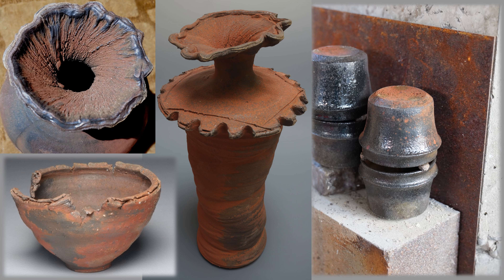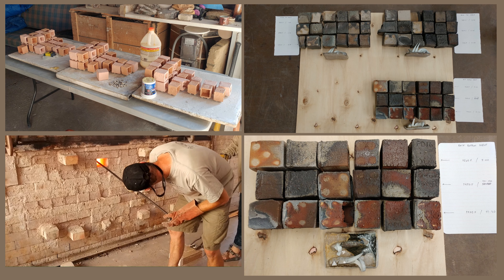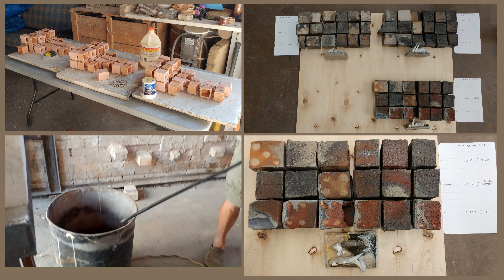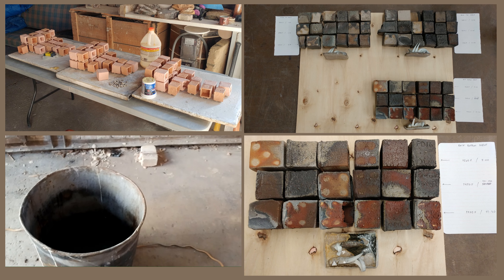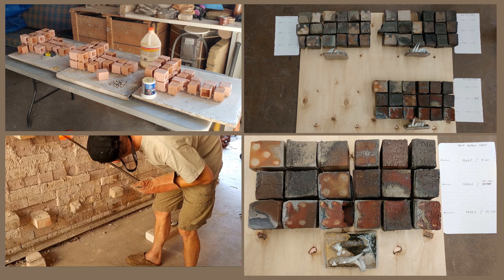On this slide, we see some examples of reduction cool reds on wood-fired pots, as well as a rusty piece of sheet metal on the far right. This juxtaposition is meant to highlight visual properties that reduction cool reds share with rust. Dan Murphy and I started our kiln-based research with the idea of pulling draw tiles during a reduction cool. We hoped this could be used like draw rings in a salt firing to judge when the down fire had reached a low enough temperature for the elusive reds to appear. Our tiles were actually little square cups, designed to have nice flat surfaces for microscope imaging.